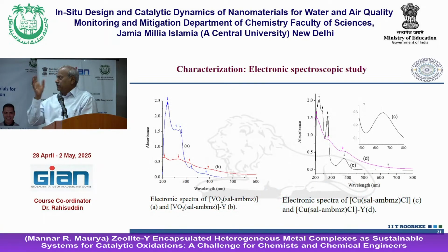Another thing is electronic spectroscopy, which is sometimes helpful, but how do you record the electronic spectra? The method I told you in the morning: grind it in Nujol nicely, make it like a suspension, like an emulsion, attach the paste in the cuvette, and in the other one use Nujol as reference. You should be able to record it, and sometimes we get good information out of that.